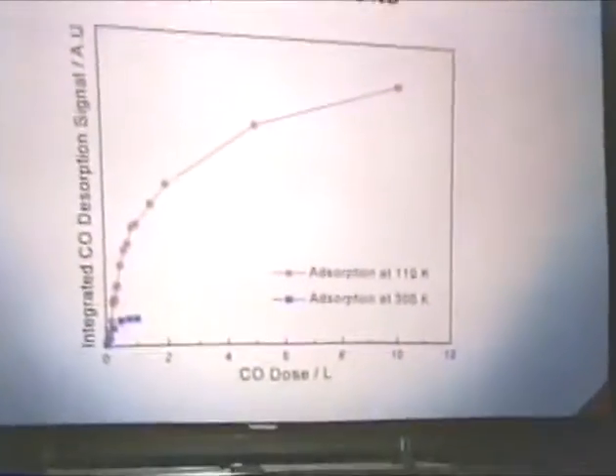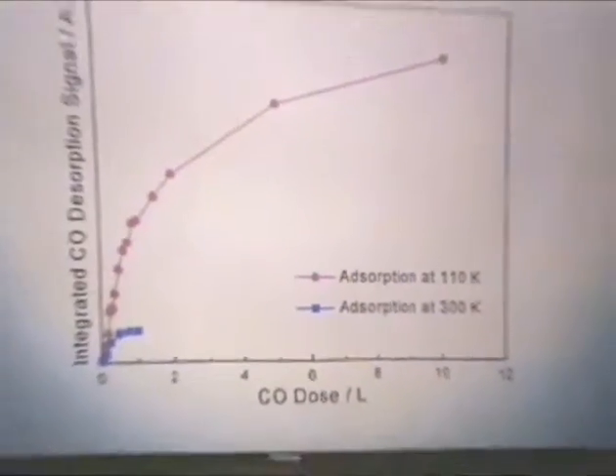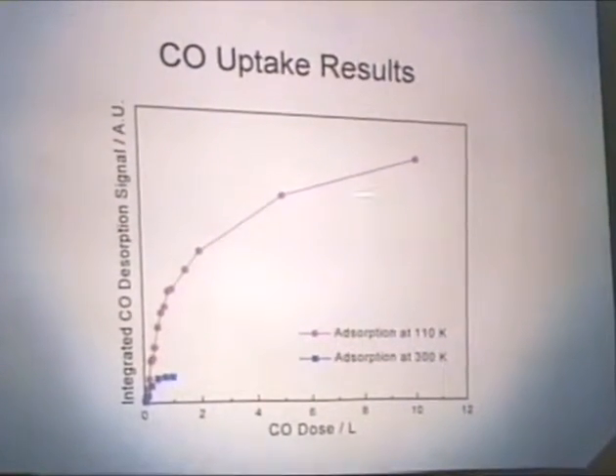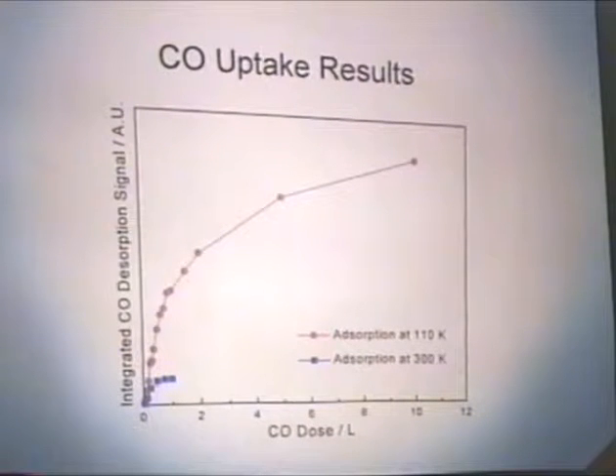If we plot the area under the thermal desorption curve versus the dose, we can get a qualitative idea of how close we are to saturation. You see for the adsorption at 110 Kelvin, which is populating 5 states, at a dose of 10 Langmuirs, the curve is bending over, indicating that we are approaching or very near to saturation. However, if you look at the adsorption at 300 Kelvin, even at a dose of 1 Langmuir, we've already saturated the 1 state that we can access at that temperature.